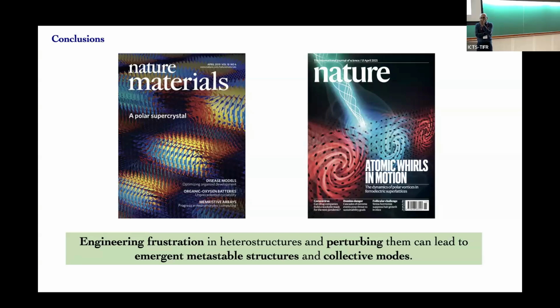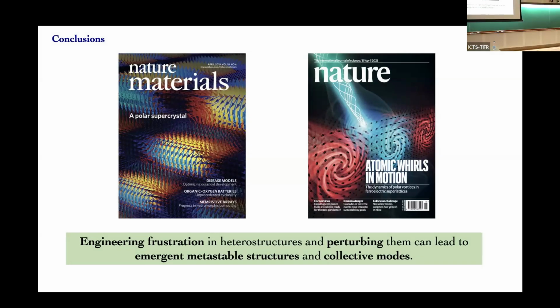I think I flashed through a last slide, but for that one-pulse transformation, you have to hit it with a certain energy, a certain fluence, and then the exposure could be short. But let's say I hit with less energy, but for a longer time, and do various series of pulses, then something else shows up. So there are four or five supercrystals that we now have. Each one can be studied for years. It just gets overwhelming after a while, but it's very rich in that sense.